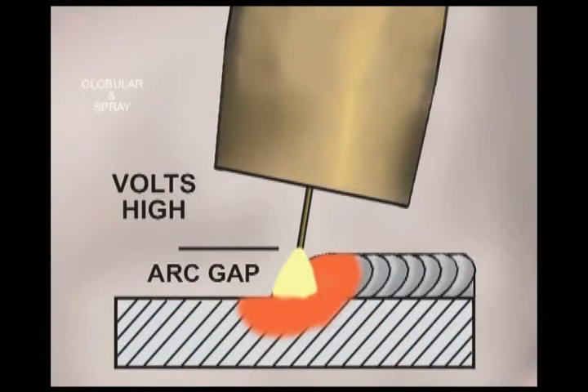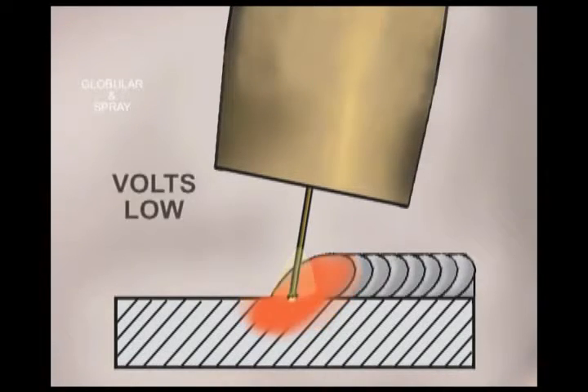The voltage regulates the actual arc length, so if the volts are set too high, the arc gap will be long, throwing heat on the molten puddle and making it difficult to control. If the voltage is set too low, the wire runs into the puddle, kind of exploding and causing excessive weld spatter. Adjust the voltage to obtain a short arc length. Globular transfer with carbon dioxide or 75-25 will produce weld spatter. You really can't get away from it.